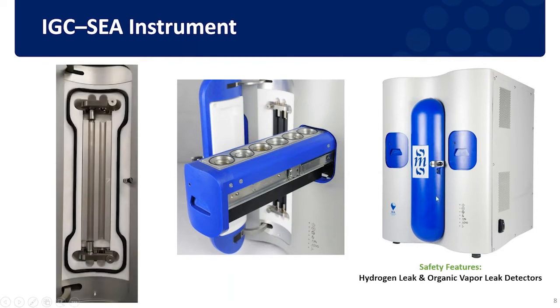And in the middle, this blue part here is the column oven. So we have a very uniform temperature distribution throughout the column with the temperature range from 12 to 150 degrees. And there are 2 different sample locations that allow you to put 2 samples at the same time, but run the experiment one by one in sequence.